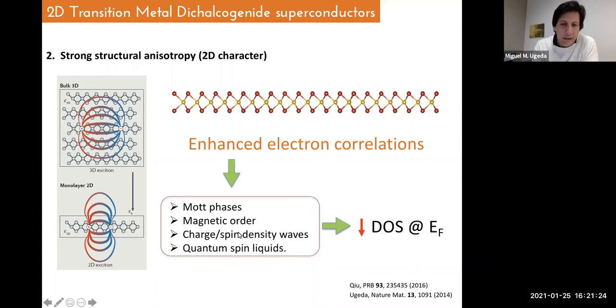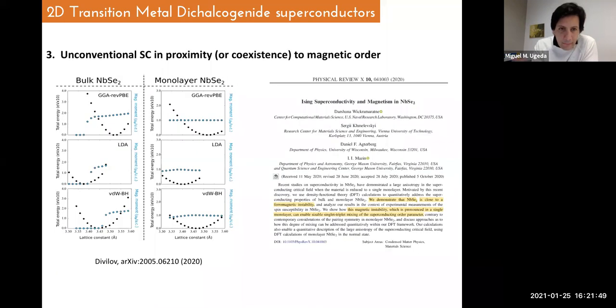However, most of these strongly correlated electronic phases usually lead to a decrease in the density of states at the Fermi level. And that is detrimental to the conventional electron-phonon coupling, and it's detrimental to conventional superconductivity because it reduces the density of states at the Fermi level. Finally, as I said, superconductivity in general is close to magnetic order in unconventional superconductors. And this is something that we don't have the experimental proof of yet, but there are a couple of recent papers claiming so, in particular for niobium diselenide.